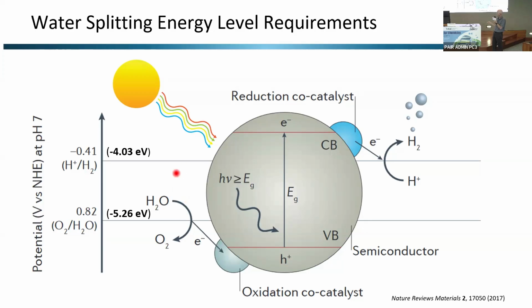And you need a minimum band gap of 1.23 electron volts for this process to occur. And I say that as a minimum band gap because these processes have a built-in overpotential. So you actually need closer to 2 electron volts in order to have enough thermodynamic drive, because this is a 4-electron process. So you need quite a lot of overpotential to drive the oxidation reaction, a little bit less for the reduction. But nonetheless, when you start to consider 2.5 electron volts to drive this process, and you realize the most abundant part of the solar spectrum is around 1.4 electron volts, there's a real mismatch there.